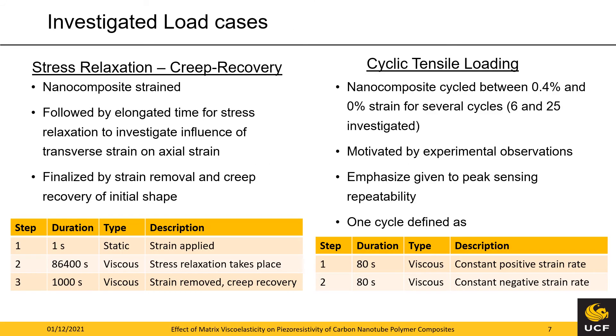The first investigated load case consists of a uniaxial extension along the x-direction over 1 second, followed by a 24-hour stress relaxation simulated as a viscous step, and is finalized by the removal of the strain and the creep recovery over 1000 seconds. The focus here lies on the influence of the transverse strain during the stress relaxation step and how it influences the resistance in the axial direction. The table on the lower left-hand side summarizes the simulation parameters.